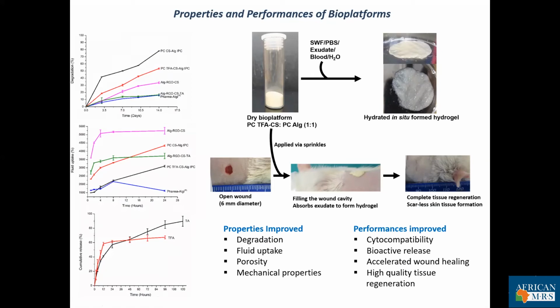So basically, once your scaffold is placed in the wound, it takes up all that exudate to form the hydrogel, and ultimately resulted in complete tissue regeneration, very importantly with scarless skin tissue formation. We also saw improved cytocompatibility, bioactive release, and what we were aiming to achieve was the enhanced or accelerated wound healing with high quality tissue regeneration as observed histologically as well.